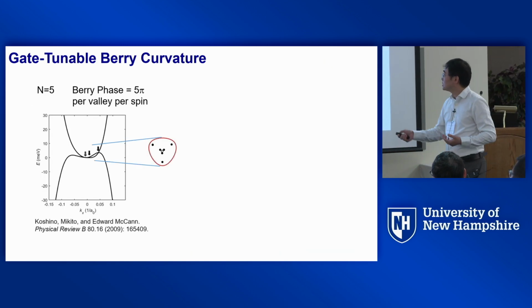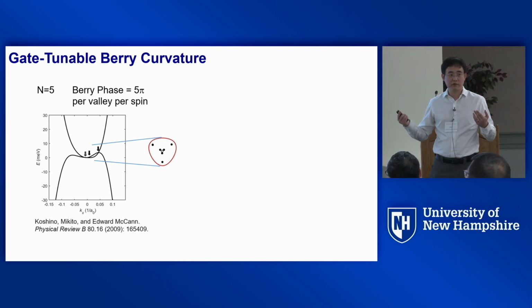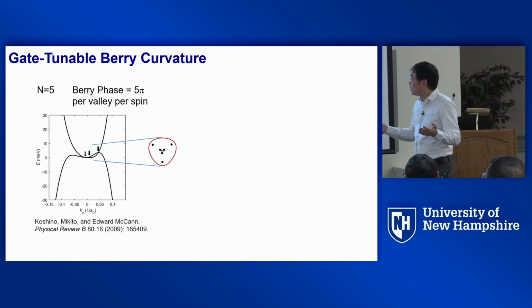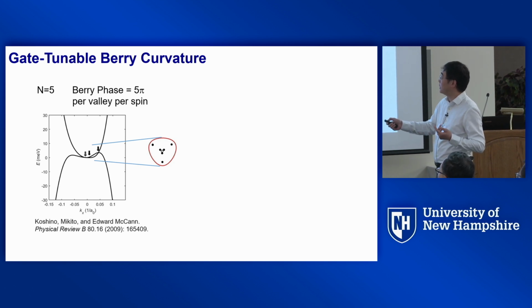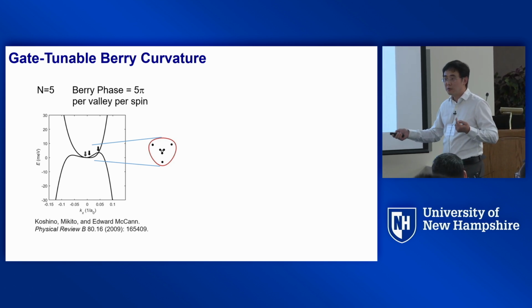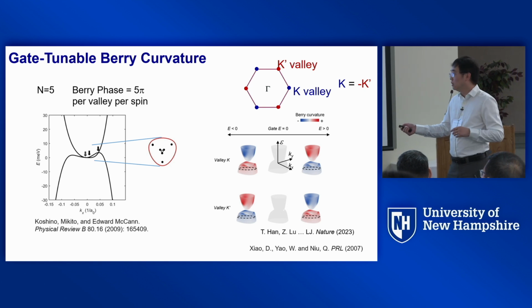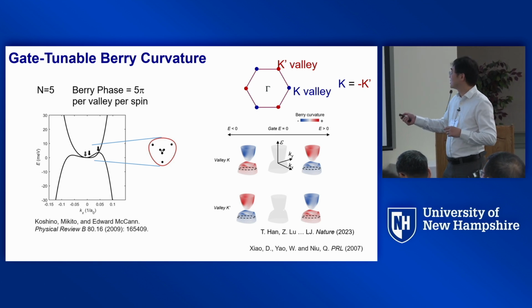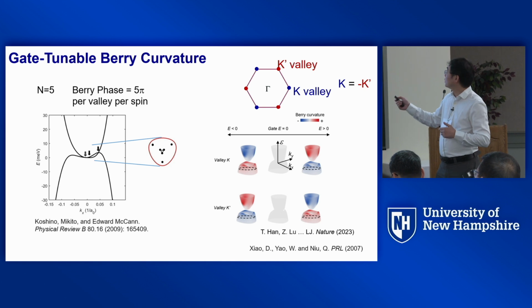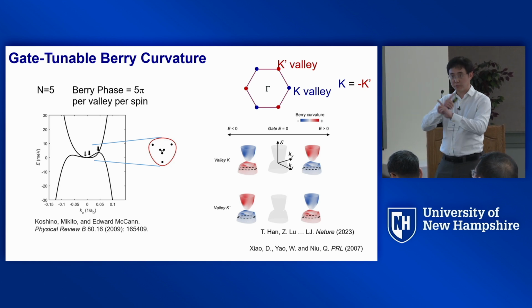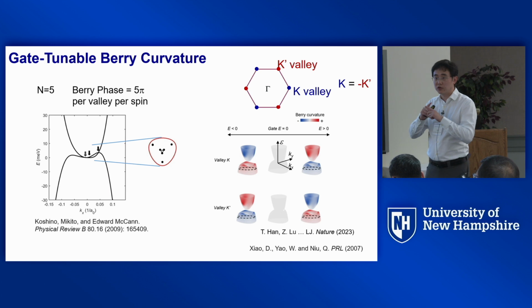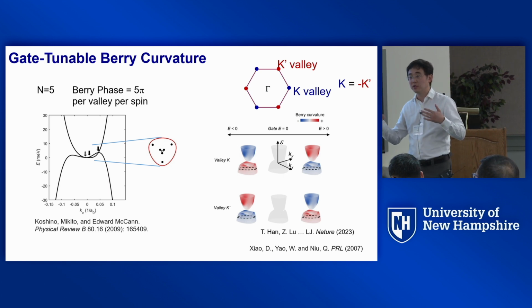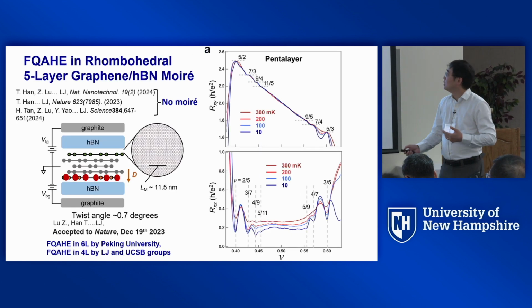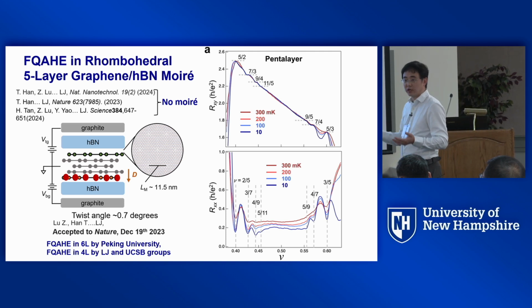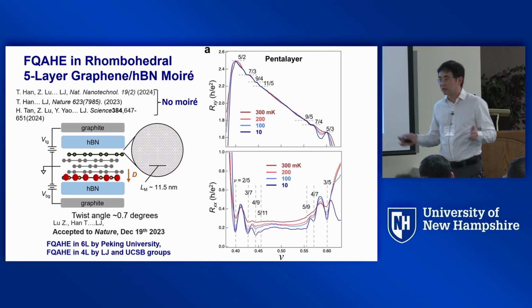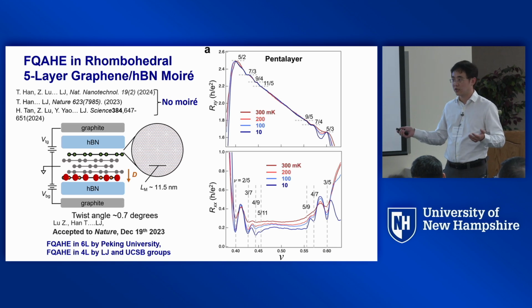On the other hand, this structure also gives you a lot of tunable Berry curvature because the band crossing points are topological objects, right? 5-layer graphene has a Berry phase of 5 pi per valley per spin. By opening up the band gap by gate tuning, you can also control the Berry curvature distribution in states near the band edge. And graphene has K and K prime valleys. They are time reversal pairs, so they always cancel each other if you populate K and K prime equally. So we think this is a good system to look into. At that point, there's not much prediction of correlation of topology in such a system.